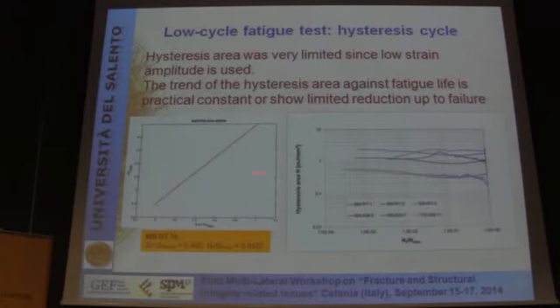Practically, the hysteresis cycle is absent because we have a very low strain amplitude. In the first cycles, there is some plasticization. In fact, the stress ratio is negative. Calculation of hysteresis area was affected by a large error.